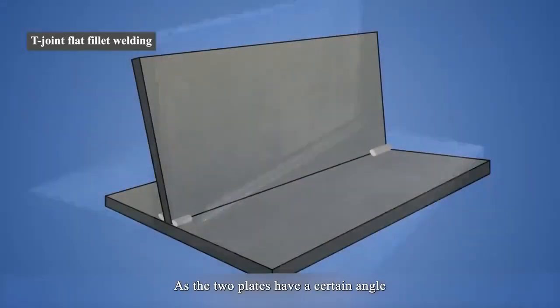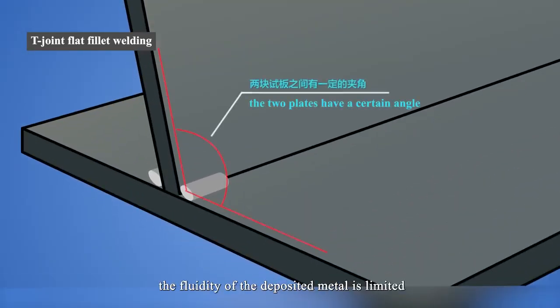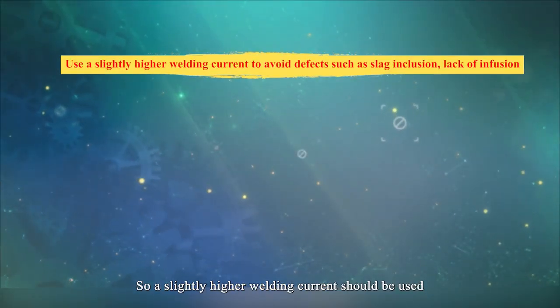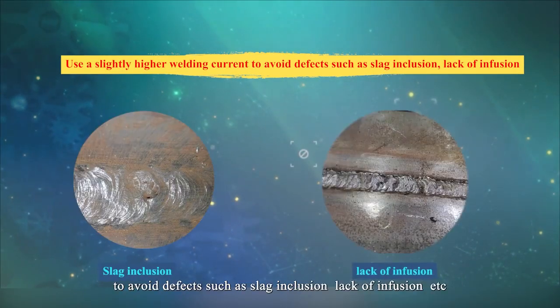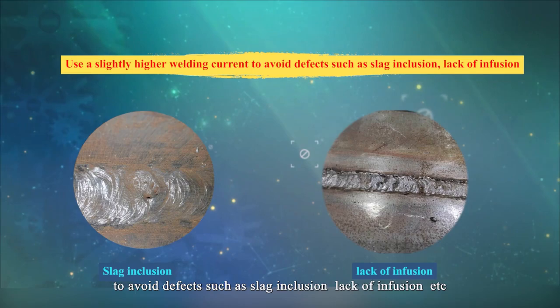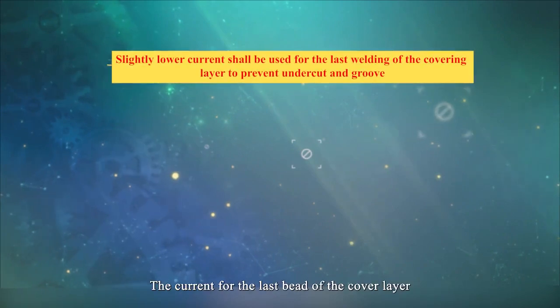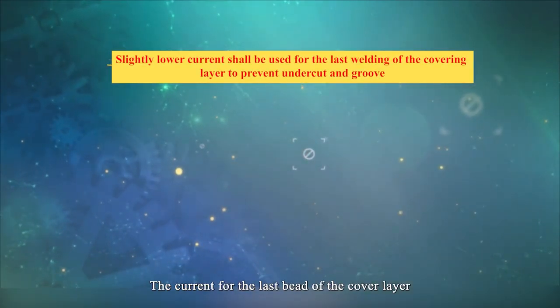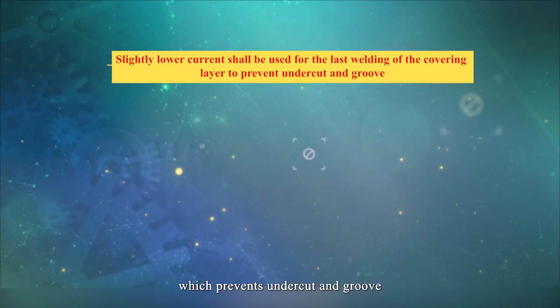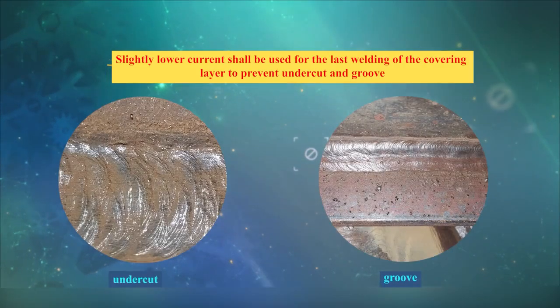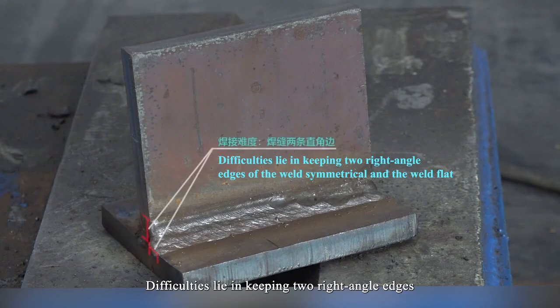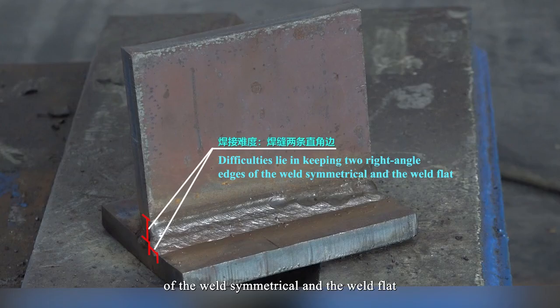As the two plates have a certain angle, the fluidity of the deposited metal is limited, so a slightly higher welding current should be used to avoid defects such as slag inclusion, lack of infusion, etc. The current for the last bead of the cover layer should be slightly lower than that for other beads, which prevents undercut and groove. Difficulties lie in keeping the two right-angled edges of the weld symmetric and the weld flat.